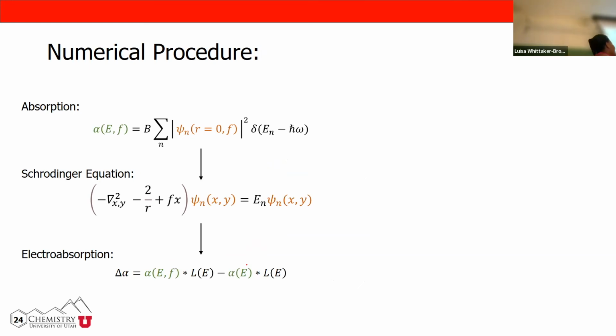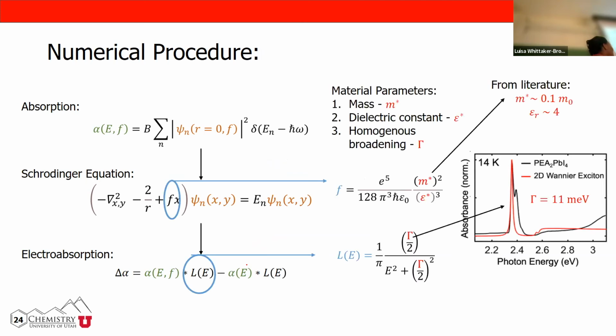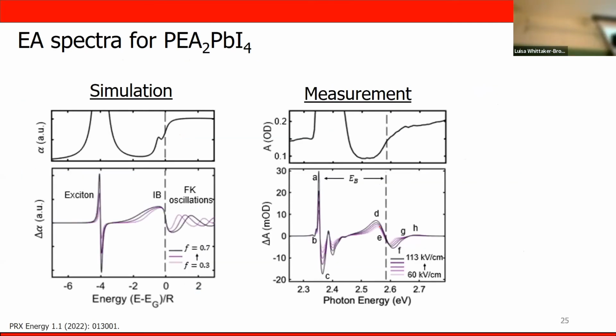The problem with that is that, again, we have to rely a little bit on the literature because now the electric field is related to the effective mass. So we have to use the effective mass that is in the literature. And then the same for the dielectric constant. And then we have this homogeneous broadening, which is from the absorption features that we are getting from our signal, okay?